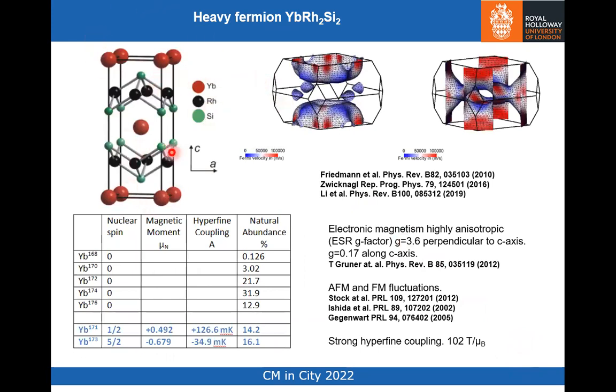So this heavy fermion is a tetragonal system. The Fermi surface hasn't been measured, but it's rather complicated, consisting of various pieces. Here's this jungle gym piece. The effective mass varies hugely over the Fermi surface. So the blue regions are the regions with low Fermi velocity, hence high effective mass. And the relevance of this to the observed properties of YbRh2Si2 is, as far as I can make out, being new to the field, not discussed an awful lot in the literature, maybe because this object is a very complicated object.